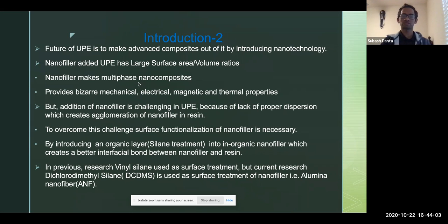In previous research, vinyl silane was used as surface treatment, but in the current research, dichlorodimethylsilane is used as the surface treatment of the nanofiller, that is alumina nanofiber. So this research is basically a comparison with previous research of vinyl silane treated alumina nanofiber.